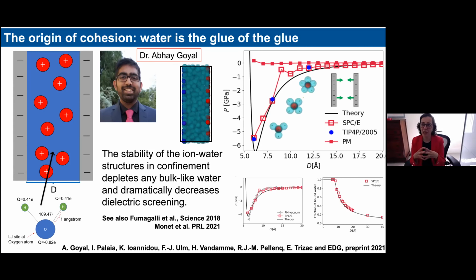Basically, what happens is that there are ion-water structures that become specifically stable at different degrees of confinement, and these structures do two things. They optimize the packing of the confined system between the two charged surfaces. They also dramatically decrease the dielectric screening of water in this very small space, because all the water there is bound in this ion-water structure. And this makes the cohesive interaction between the two surfaces grow by two orders of magnitude.